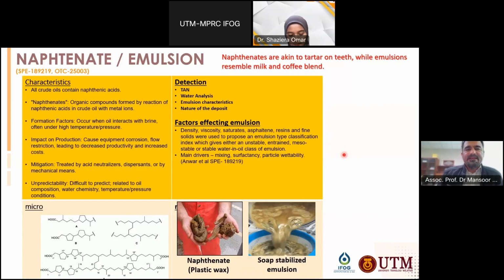So this is naphthenate, and of course, naphthenate and emulsion. The characteristics: naphthenates are complex organic compounds present in crude oil, specifically in the acidic component of oil. They can cause operational problems in oil and gas. For the detection, we can use total acid number and water analysis. We can use emulsion characteristics for the emulsion, of course. Factors affecting emulsion are the density, viscosity, and also the amount of saturates, asphaltene, resin, and fine solids. This can actually affect the